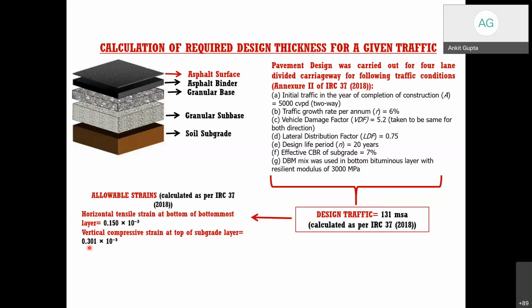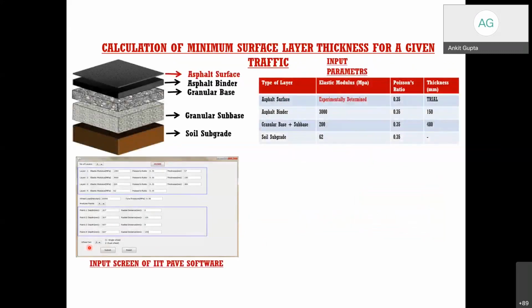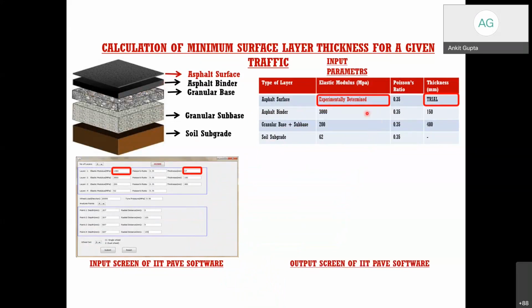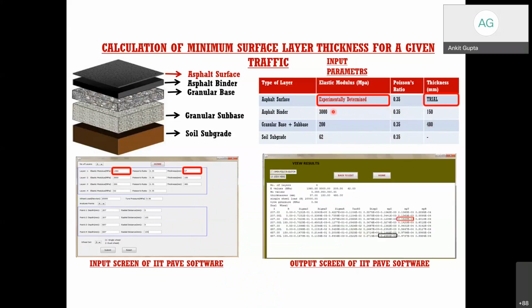Now we did the analysis. For the analysis, we have used the IIT Pave software. Before going on to the analysis, what we did is that for the binder surface, that is the DBM layer, we fixed the thickness of the DBM layer as 150 mm. We have fixed the thickness of the granular base and the sub base as 480 mm. We have assumed the Poisson's ratio. We have assumed the elastic modulus. Okay, all these values have been assumed.